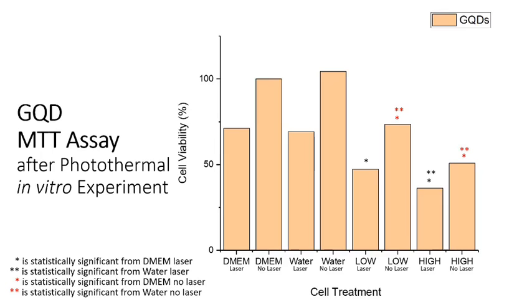With our GQDs, we get similar statistics as our molybdenum disulfide, but if you'll notice the difference between the low that got treated with the laser and didn't, and the high that got treated with the laser and didn't, we see something very different there, and I'll get into that in just a minute.